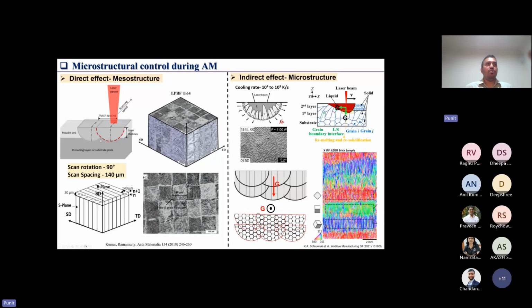The signature comes from the melt pool when you are melting the material, and this melt pool can have a signature effect. For example, this is an image of titanium 64. In this case we were using a scan rotation of 90 degrees, and because of that you can see the scans overlapping after each layer, and you can have these long columnar grains, and on the top you can see the microstructure reflects your hatching strategy. This kind of microstructure is what I'm referring to as mesostructure, and this is a signature effect of the building process that we are using.